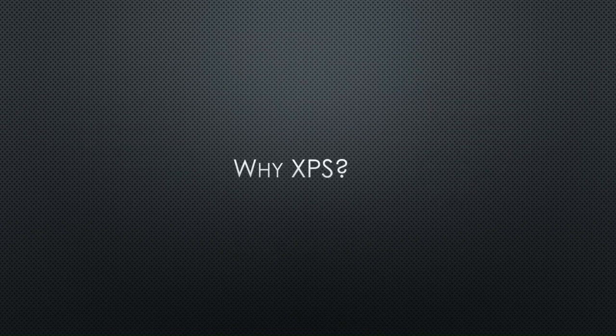So, why XPS? Why use this technique over another? XPS excels at probing the top 5 to 10 nanometers of a material surface and providing detailed information about the elemental composition and oxidative states of that material. The level of surface sensitivity is crucial for studying the mechanically exfoliated van der Waals materials, where surface contamination could be a factor and affect performance. The ability to quantify not only the elements present but also their relative concentrations and chemical states sets XPS apart from any other surface analysis technique. Also, XPS is nearly entirely non-destructive, and this is important, especially when you're handling high-value 2D materials.